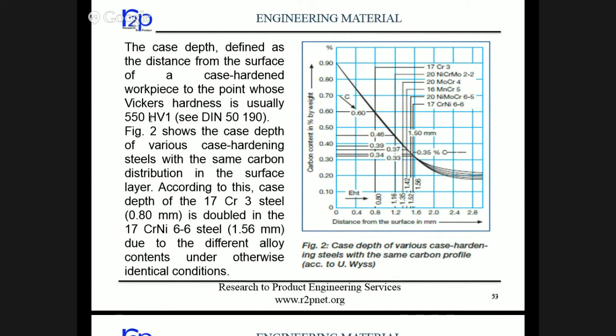So hardness will reduce, and generally this 550 HV is the criteria, or the other criteria is that the hardness where the case depth is defined will be 80% of the surface hardness. So if on the surface we are targeting 60 HRC, the case depth is defined where it is 80% of 60, that's 48. So 48 HRC, that depth is the case depth. So either 550 HV or 80%.